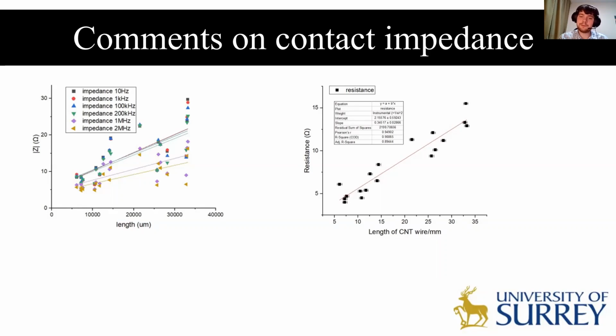However, if we compare the results for impedance with the results we got for the resistance of the contacts, we can actually find that it's different by around 2 ohms, which is greater than the uncertainty. This seems to imply that the contact impedance does have a reactive part to it. This might play a part when considering high frequency signals, although for my audio frequency range, this won't affect anything. For the audio frequency range, the contact impedance can be said to be effectively constant.